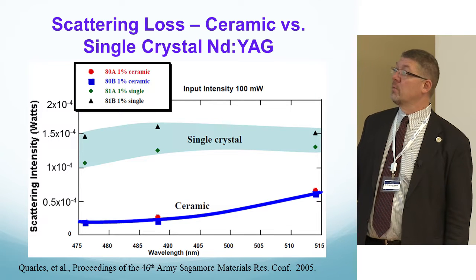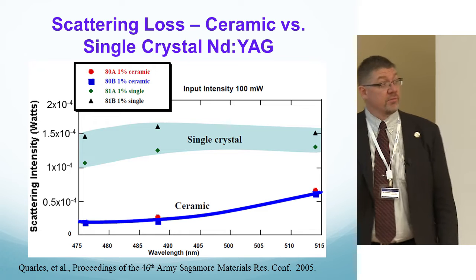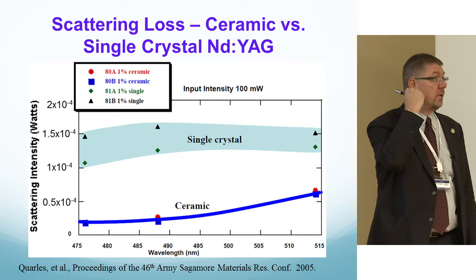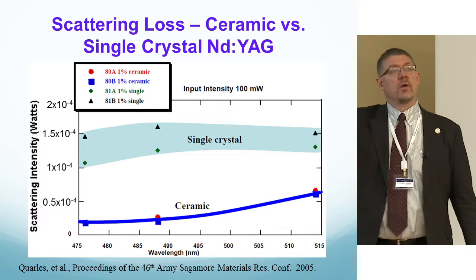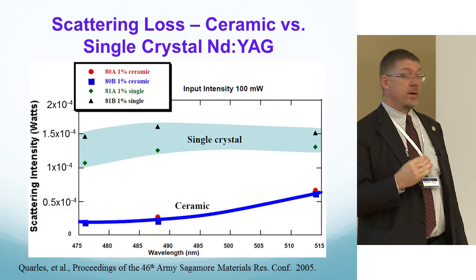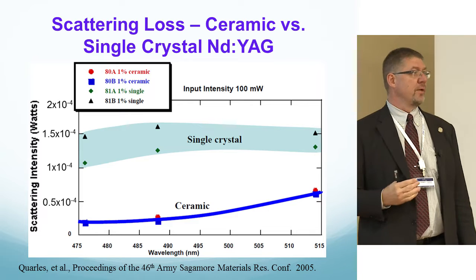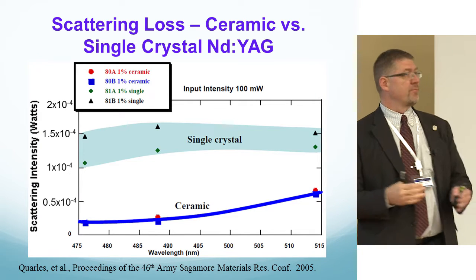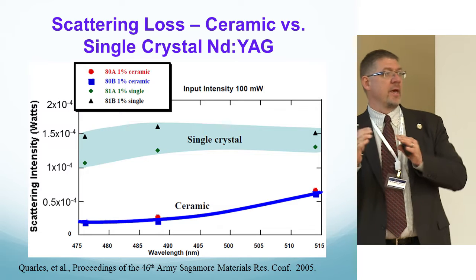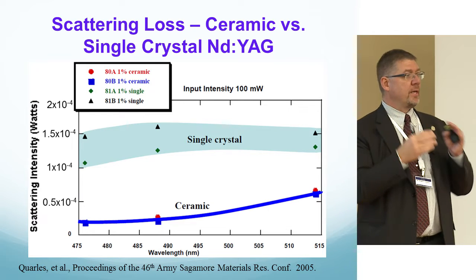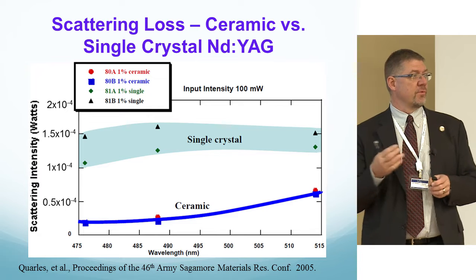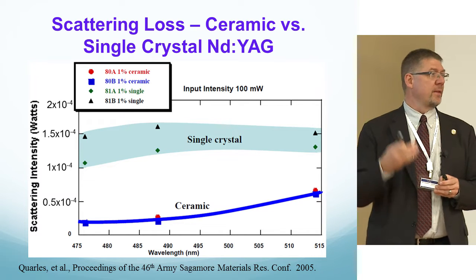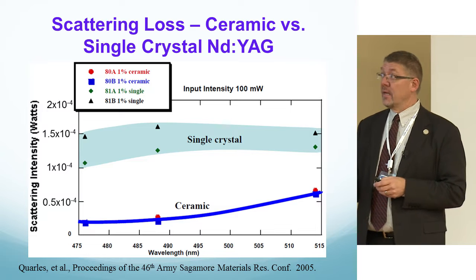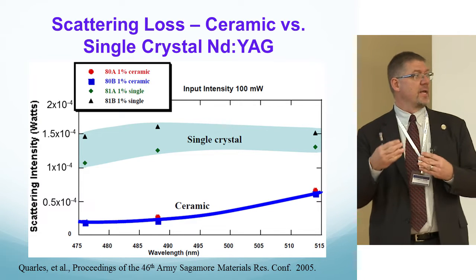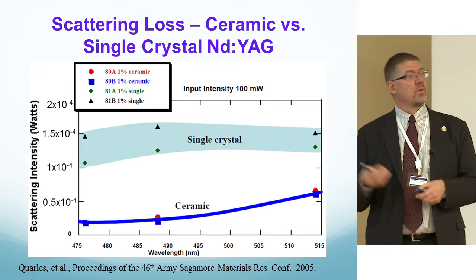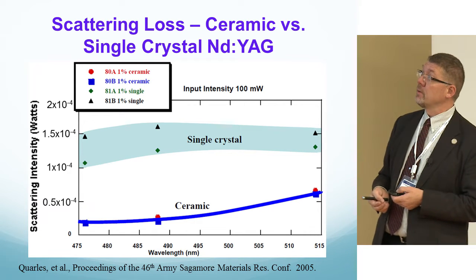After about 3 years of working with Konoshima, this was their scattering loss. It was a full factor of 2 lower than single crystal. So they had the ability to take this material, drop it into a laser, and have threshold drop by almost a factor of 2 in a commercial laser system overnight. And that makes a big difference when you're talking about running your diodes right at the edge of burning out or trying to keep your power supplies operational for a longer amount of time. You want to be able to dial back the amount of light coming out of those diodes as much as possible. And if you gain a factor of two because your Findlay-Clay analysis shows that the losses are now lower, that's a big savings for the laser companies.